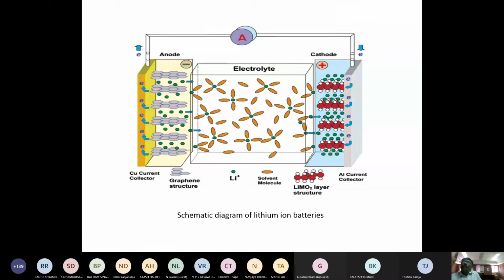So if you open any lithium ion battery, it will have three components. One is the cathode and another is the anode, which are separated by a porous polymer polyolefin membrane, soaked in a non-aqueous liquid electrolyte. Generally the liquid electrolyte is composed of some carbonate solutions with lithium hexafluorophosphate dissolved in it. So when you discharge and charge, the lithium ion will migrate between the anode and cathode.